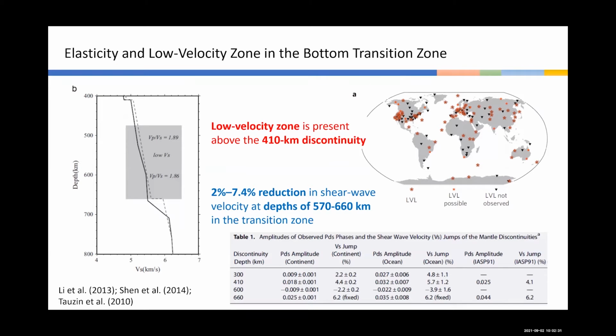And especially in recent years, seismologists have identified a lot of velocity anomalies at various depths or locations of the Earth. Here, I just show you 2 examples. One is a low velocity zone that is present above the 410-kilometer discontinuity. The other one, they also observe about a 2 to 7% reduction in shear wave velocity at the bottom of the transition zone. So this tells us that if we want to decipher the origin of those velocity anomalies, we have to have better knowledge about the influence of composition variation on the elasticity or the sound velocity of different minerals. So that's the reason we have to do experimental measurements to try to decipher the formation mechanisms of those velocity anomalies.